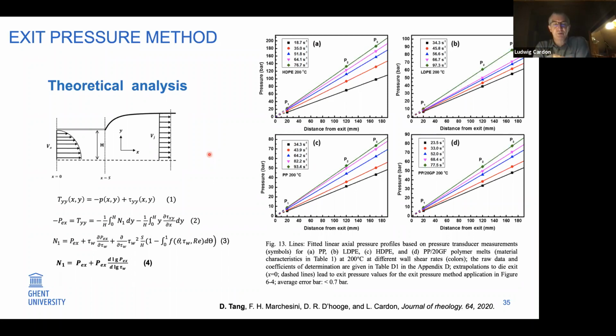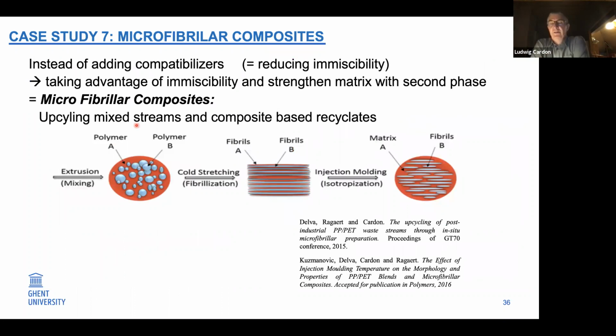And that's also the correlation, briefly to mention, that we do in die design. Inside, for instance, a co-extrusion die, they try to mimic a uniform flow inside the die, and they try to avoid a higher flow in the middle of the die and a lower flow at the borders. So this is also a reverse you can do. Based on this information, you can redesign the internal structure of a die so that this pressure or speed distribution is equal when the polymer finally exits the die, and you don't initiate a die swell. So that's briefly how we interact with technologies. That's very briefly on die design and rheology investigation.